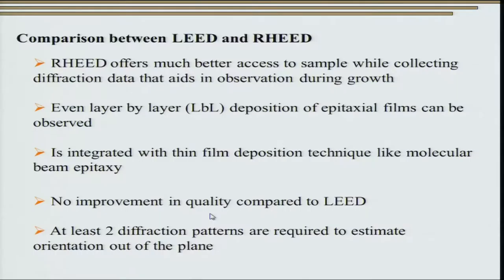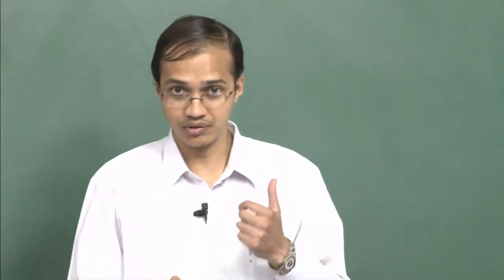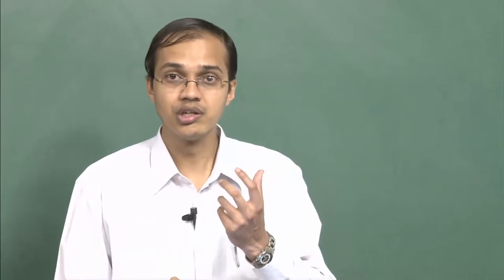Reflection high energy electron diffraction is integrated with thin film deposition techniques like molecular beam epitaxy and used routinely in the semiconductor industry. However, there are some disadvantages compared to low energy electron diffraction: the quality of the diffraction pattern is not as good. Also, to obtain complete information about the film in the entire plane — its symmetry and structure — we need to rotate the sample, since information is obtained in only one direction. Rotating the sample gives complete two-dimensional information.